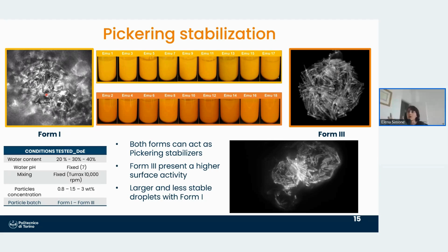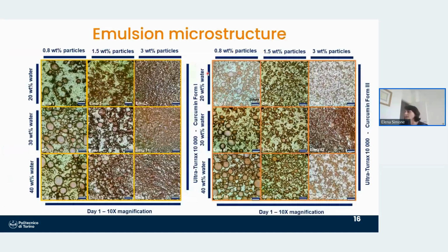So this is more hydrophobic. Those particles tend to stay a little bit more in the oil rather than at the interface. And this means, disappointingly, worse images, but also slightly worse stability of this form 1 emulsion, although they could still stay for quite long, several months, nicely separated into the two phases.